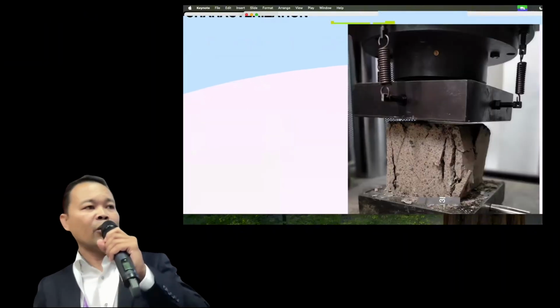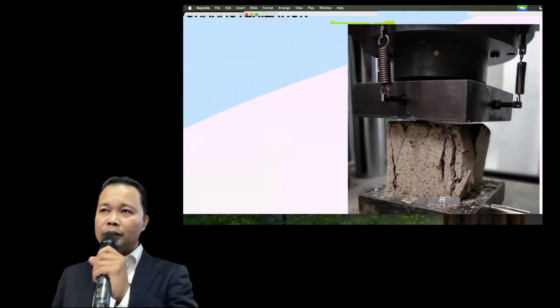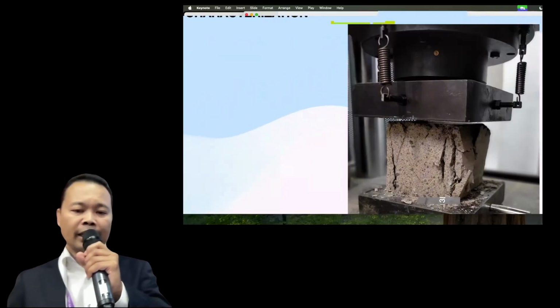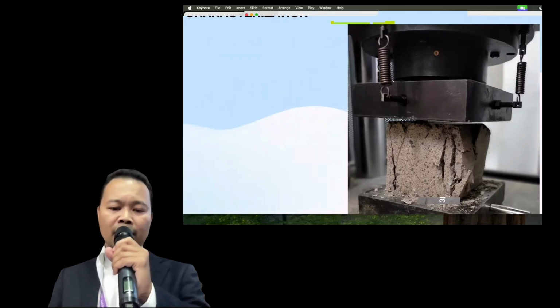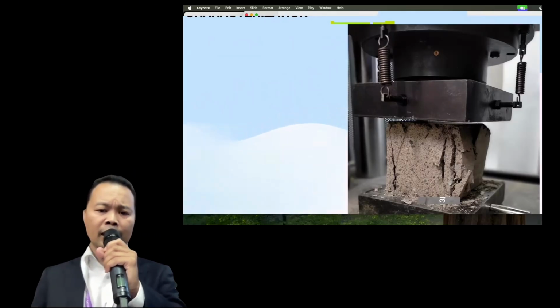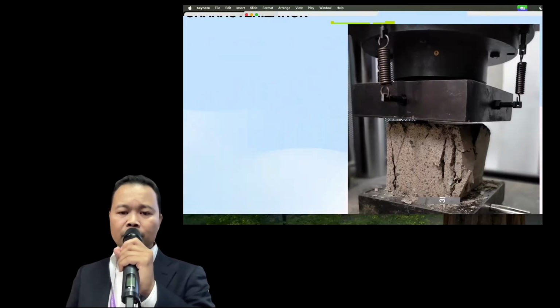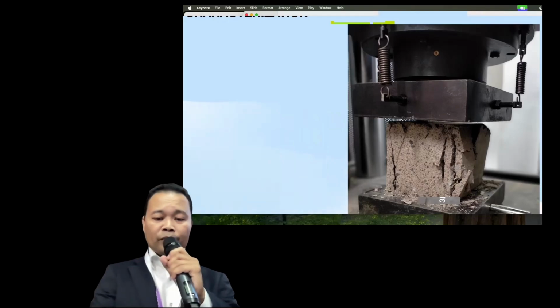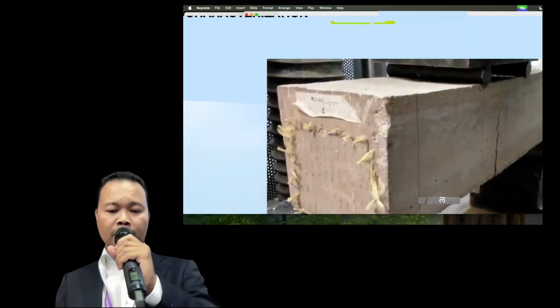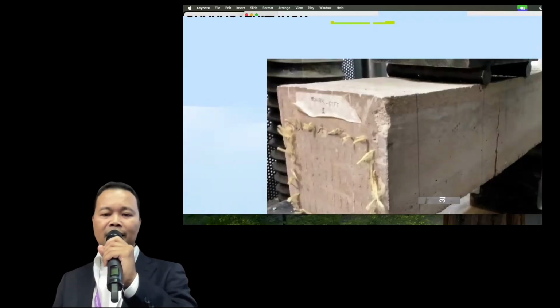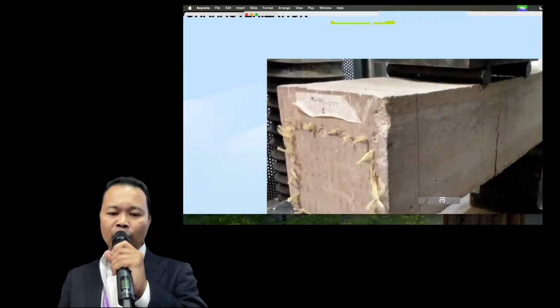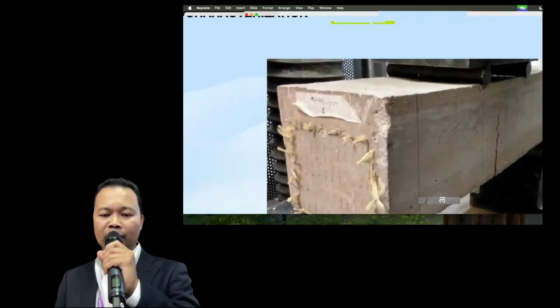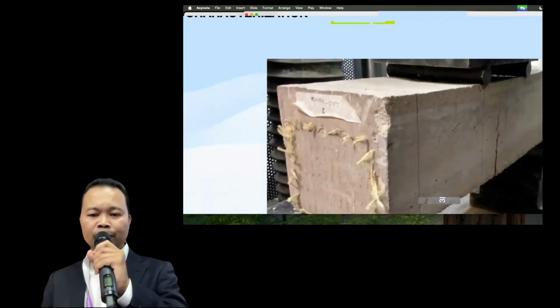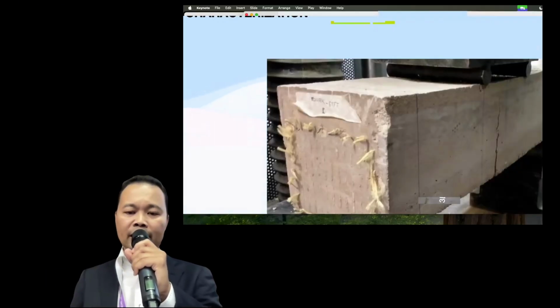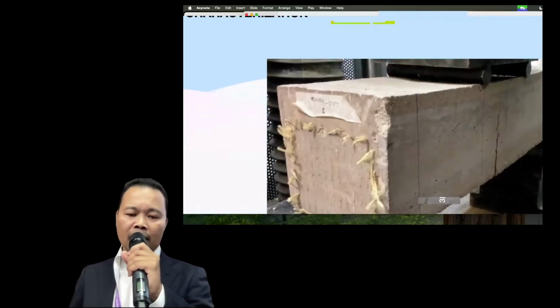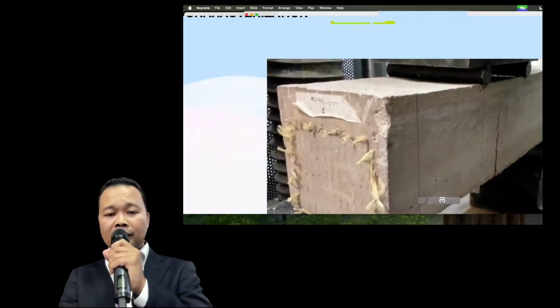For the compressive test, typically we prepare the sample in a cubical form with a size of 15 centimeter by 15 centimeter, and then we apply the load. The compressive strength is considered as when the sample breaks under a particular maximum load. In a flexural test, we prepare the sample with the size 50 centimeter by 15 centimeter, and then we go for a test. We're using a 3-point bending test, and we apply the load at the center, and the maximum load required to break this sample we consider as the flexural strength after considering other parameters.